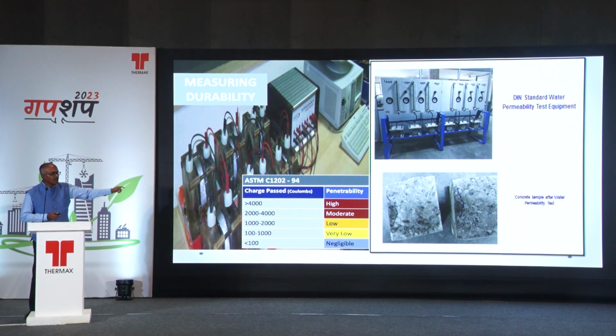So here in the water penetration test, we are looking at the limit that the water should not penetrate beyond, or at least should not touch, the reinforcement bar. That is where the corrosion starts. So the maximum is the cover to the reinforcement bar, but if it happens to be a strategic structure, it has to be much lesser than that. So these tests are there.